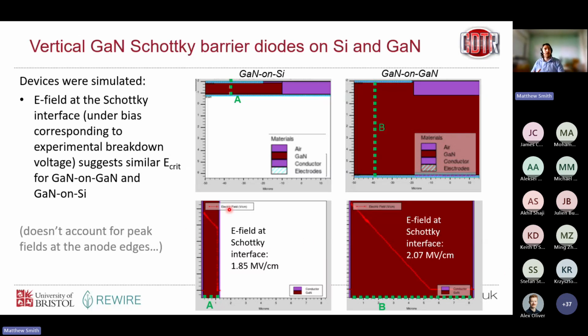Now, this simulation isn't perfect. It doesn't account for edge termination differences, which is something that we're working on. But it would seem to suggest that despite the 1,000 times higher dislocation density that we have in GaN on silicon, we don't see a 1,000 times decrease in our breakdown, in our critical electric field. It seems to be relatively stable there.